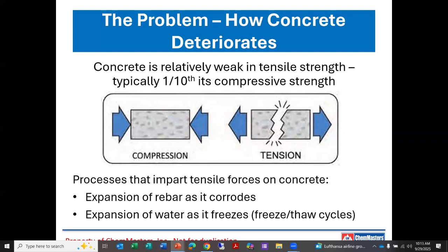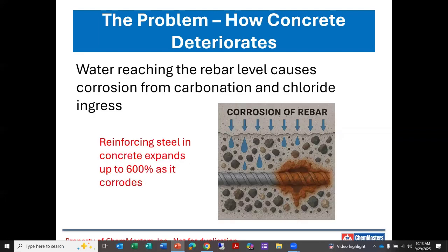which is considerably less. And as the expansion of corroding rebar occurs, and the expansion of water as it freezes, it imparts those tensile forces on concrete, and that's where our damage is done. So water reaching that rebar level time and time again, and as the passivity protection is lost, the rebar will begin to corrode and expand up to 600% as that corrosion occurs. That's a lot of expansion. That's a lot of force, internal force and tensile force on that concrete. And concrete is not designed to handle that.